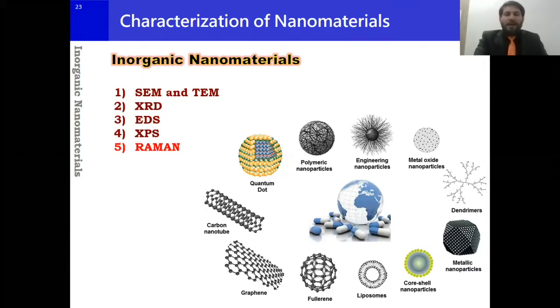Then Raman, people are also using Raman, but normally, if you have XRD, you don't need to use Raman. So now I'll tell you which techniques. Let's say a person is making a certain molecule. Normally you need to have SEM and TEM, and then XRD is mandatory, and XPS in many cases is also important. EDS comes from the SEM instrument, so you don't need to do it separately. Within the SEM, you can have the EDS facility, and after doing the SEM imaging, you can just run the EDS, and it takes, I think, hardly 10 minutes to have one analysis.